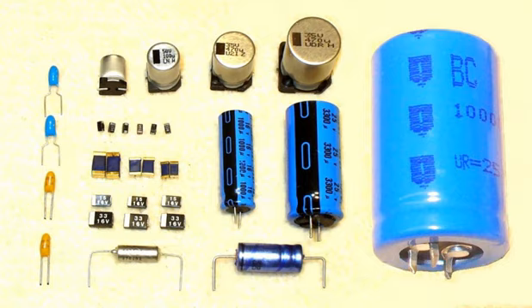Non-solid electrolytic capacitors using organic solvents like GBL as electrolyte do not have problems with high leakage current after longer storage times. They can be stored for up to 10 years without problem. Storage times can be tested using accelerated shelf life testing, which requires storage without applied voltage at the upper category temperature for a certain period, usually 1000 hours. This shelf life test is a good indicator for chemical stability and of the oxide layer, because all chemical reactions are accelerated by higher temperatures.